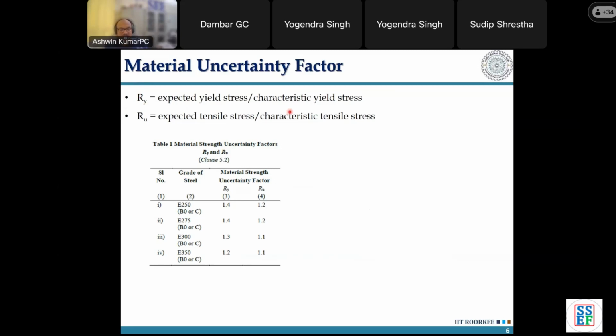which is not what you test. Like if I give you a plate in hand and I say this is an E350 grade plate of 16 mm thickness, and I tell you go and do a coupon test and tell me what yield strength you are achieving as well as what your ultimate strength is. So Ry is the yield strength value that you get from the coupon test divided by the nominal value. If you use a nominal grade of 350 MPa and test it under a coupon test, you obviously believe that 350 is the minimum yield strength mentioned by the code. So the material would have a higher strength, let's say 400. When you test it, you get a yield strength of 400 MPa, whereas the nominal value is 350 MPa. So 400 by 350 is the value of Ry.